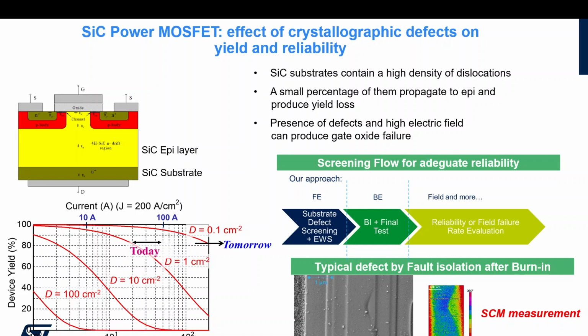This means that depending on how many defects you have on your EPI, your yield will depend on the area of the device. The smaller the area, the higher the yield. The smaller the defects, the higher the area in which you can have a good yield. So if you want to make 30 millimeter square silicon carbide, we are about here, then you have to make sure it should be in the low range of defects. Otherwise your yield, just for the fact that these defects are there, will be very low.